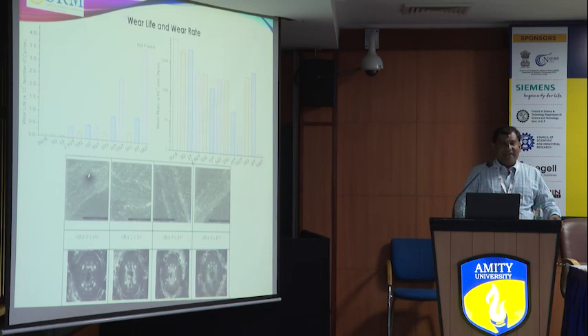So we added the liquid filler also to the solid filler. In this work, done by my PhD student, they used HBN, hexagonal boron nitride, that is known as white graphite, and they added the liquid lubricant with HBN also. So here you can see this is the pure SU8, this is the HBN, but when we added the lubricant, you can see the droplets of the lubricant over the surface also.